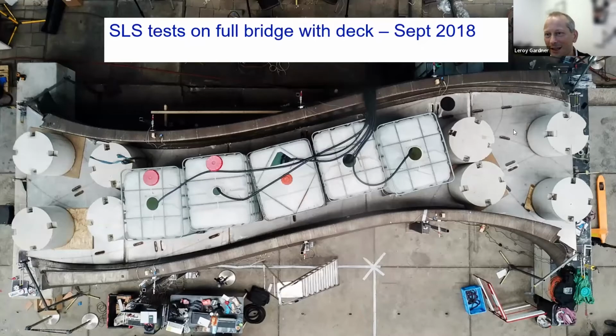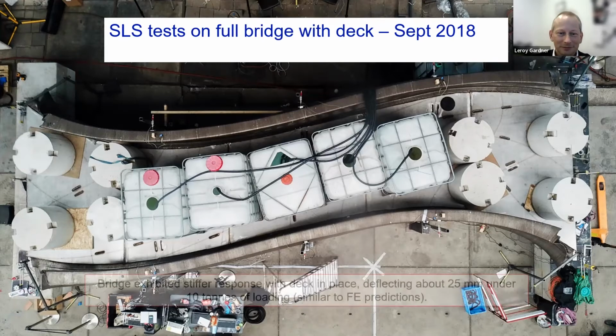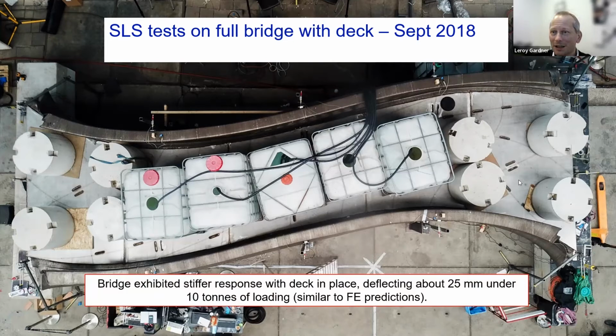Third set of tests, you can now see the deck is in place. So the deck is a stainless steel plate, but this component wasn't 3D printed. This was just welded in place to the 3D printed bridge. The loading here comes from a combination of concrete blocks and also water tanks. And the general idea with our testing is we didn't want to be physically on the bridge whilst we were putting high loads on it. And so water tanks were quite a good way of having relatively controlled means of loading without needing to be on it. The bridge was a bit stiffer with the deck in place, which is what you would expect. And it deflected about 25 millimeters under the 10 tons of loading that we applied in this set of tests.